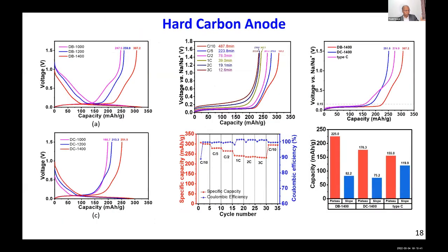Here I am moving to hard carbon production in our lab. You can see here this is actually one form of hard carbon. I will not go into the detail. This is DB. You can look at 1400 degrees centigrade is 307 milliampere hour per gram. This is DC, 1400 is 251. And I'm comparing that here with the commercially made. This is type C. This type C is commercially made, which is the pink.